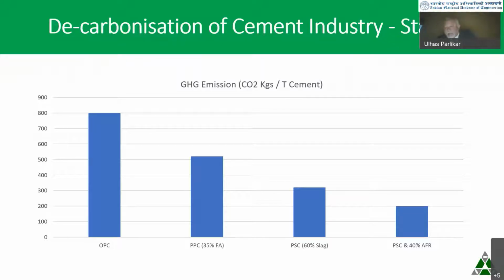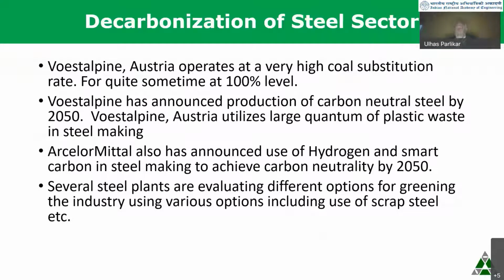And in a cement plant manufacturing PSC, which is Portland slag cement, if you replace fossil fuel with AFR, it can go to something like 200. So from 800 to 200, one-fourth, is the status of GHG emission by way of this decarbonization journey. There is a huge development which has happened in the cement sector, and that's how a large amount of CO2 reduction is happening, and it's progressing substantially ahead.